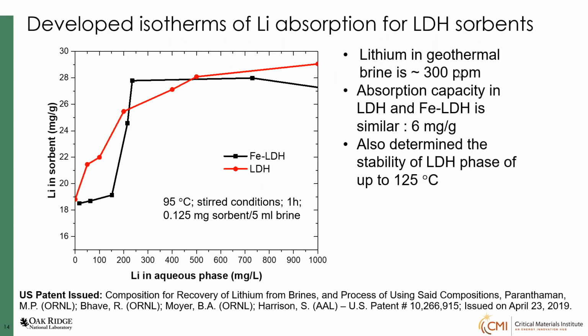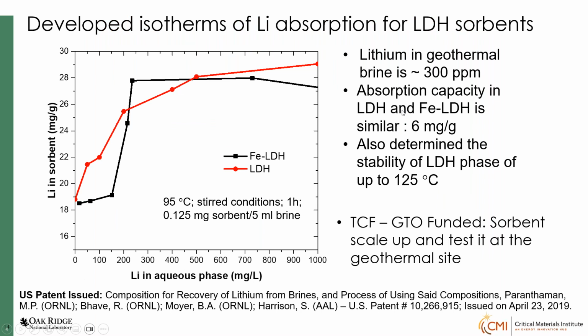So what we did was we developed some isotherms for lithium adsorption using LDH. Here we have different concentrations of lithium and the LDH and iron LDH. It's like 6 milligrams per gram, and we checked the stability. Very recently we have found that instead of LDH, we could also use aluminum hydroxide. Those have a very high record of 30 to 40 milligrams per gram or even higher. So some exciting things are coming along using second generation sorbents.